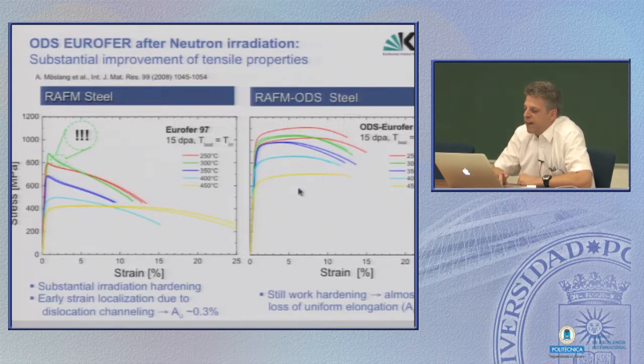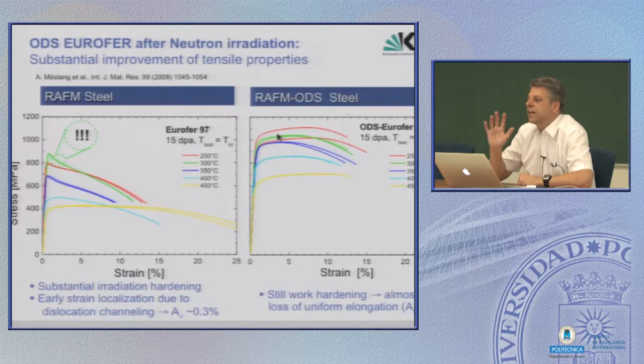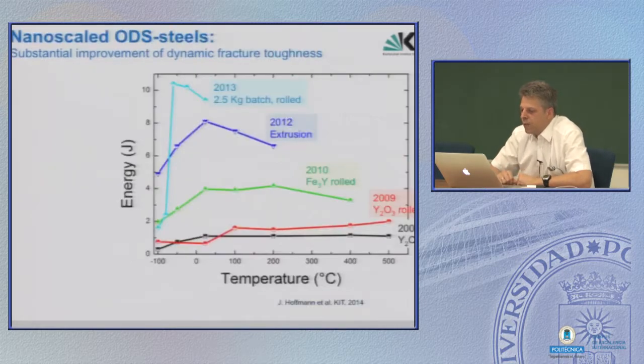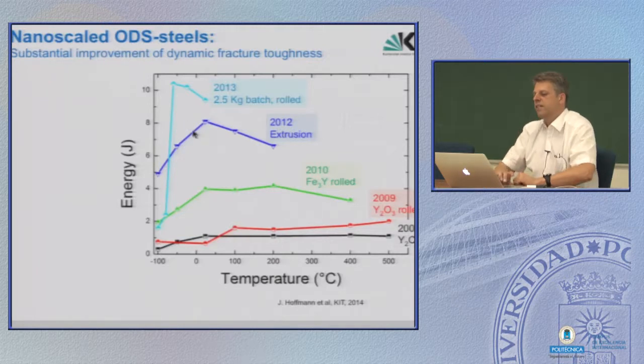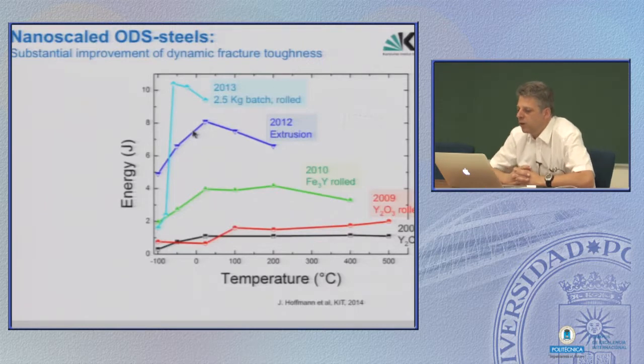If you compare this to ODS steels, you see they are also suffering from hardening, but still they have their work hardening capability. And well, these are two ways where these ODS steels behave better. There has been much progress. I have only plotted what we have done in a very small program at KIT over the last 5 years, but worldwide they have been much more successful. And well, I would say the way of how to produce these ODS steels is more or less covered. That's no problem anymore. There is only one remaining problem.